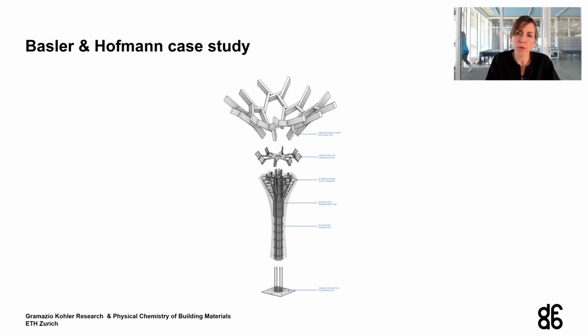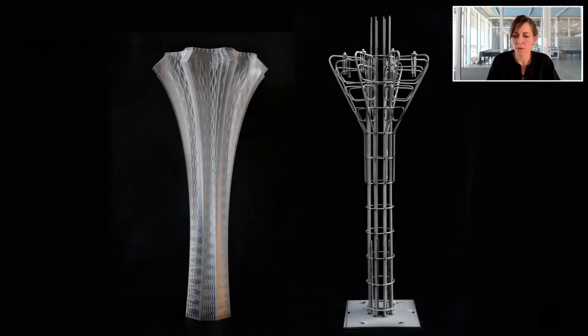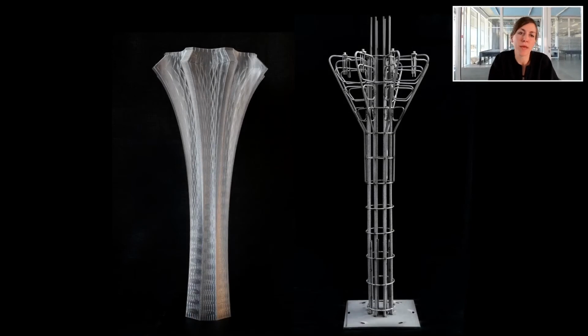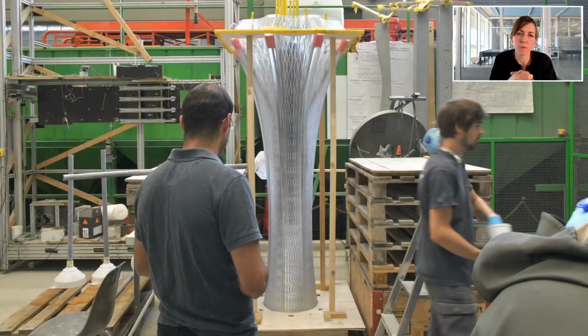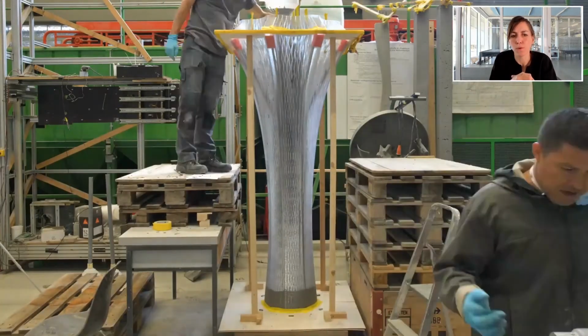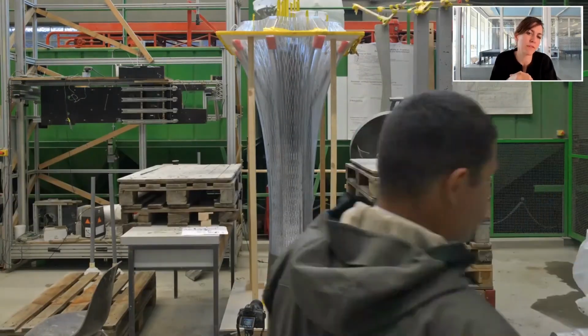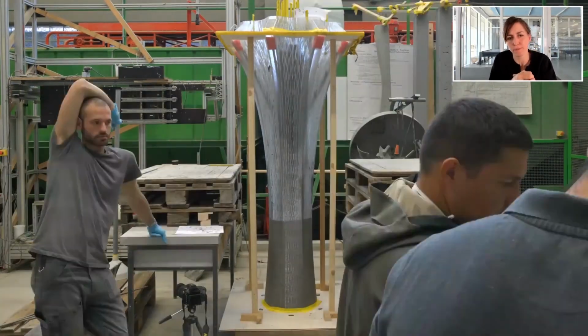However, as we were very early in the process with eggshell, and our printing facilities were way too slow, the formwork you see here took us 36 hours to print, and we could have filled it in less than 6 hours with set on demand. The things were not yet aligned. So we decided to use the set on demand in a separate process. So we started by printing, then we placed the reinforcement inside, and finally we would fill it with set on demand using our manual acceleration system, which we had developed in the past in smart dynamic casting.